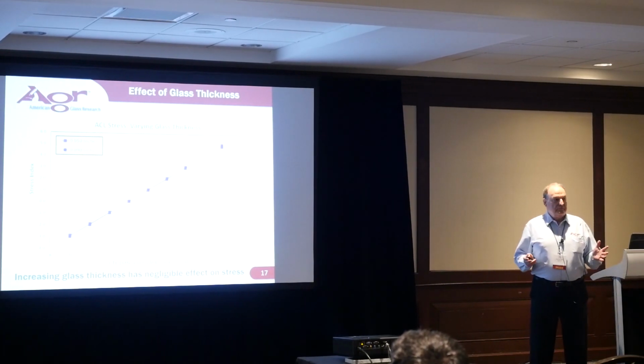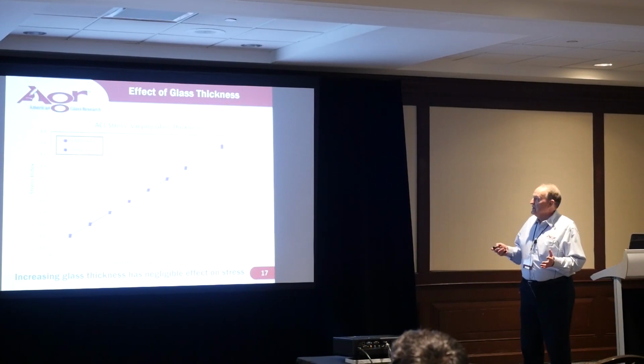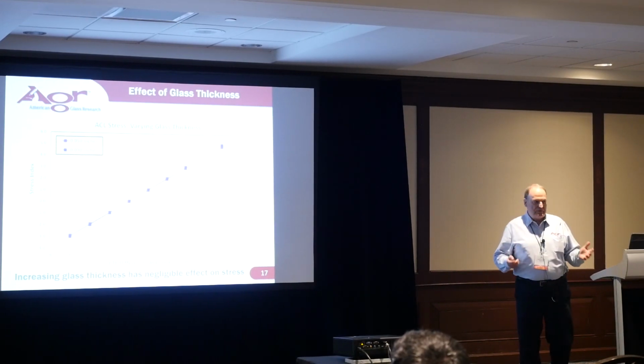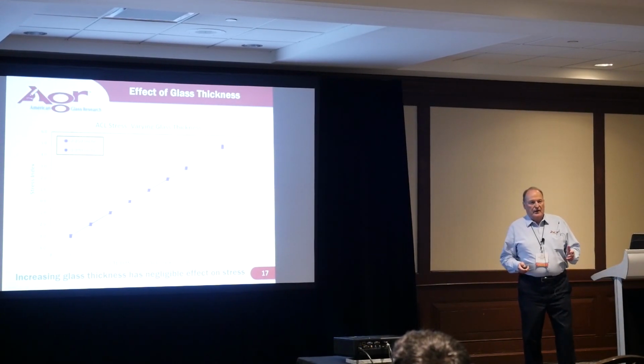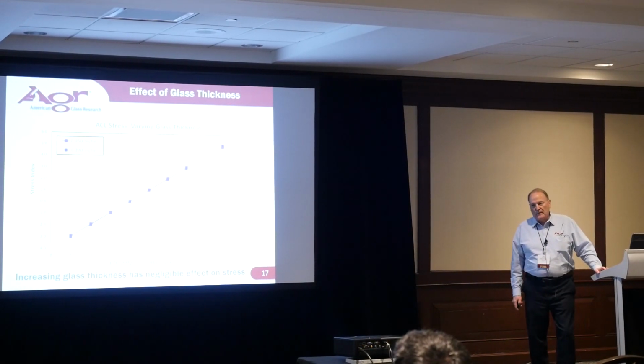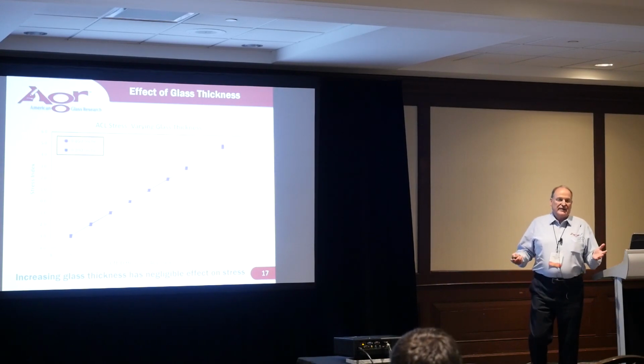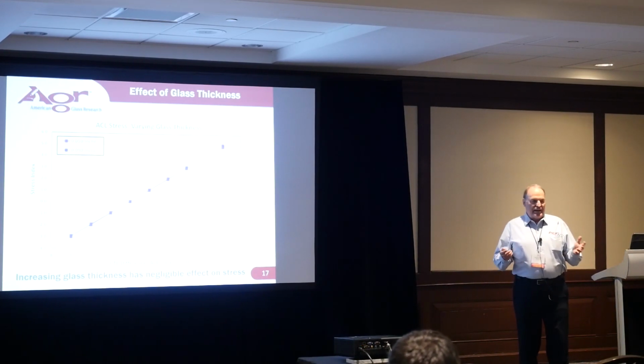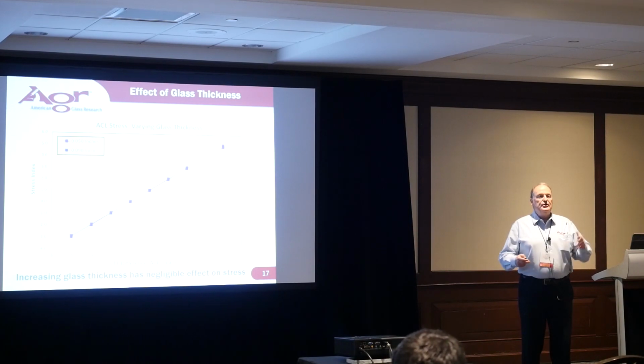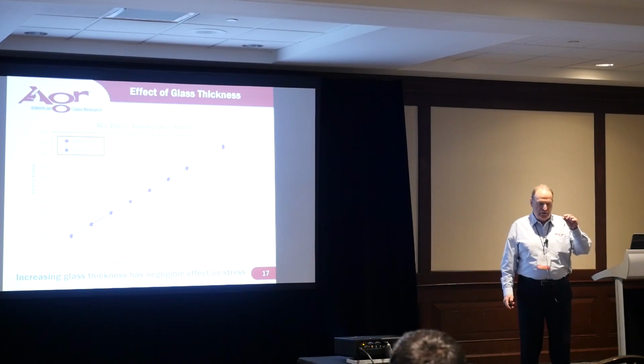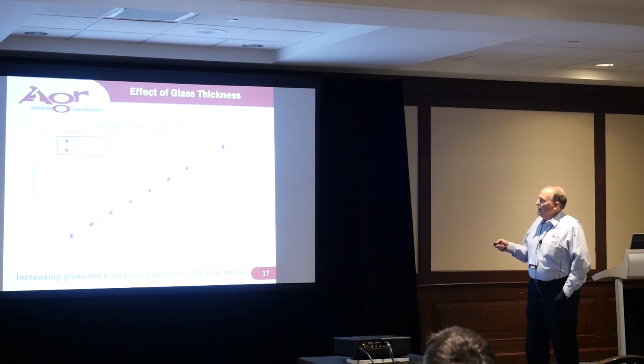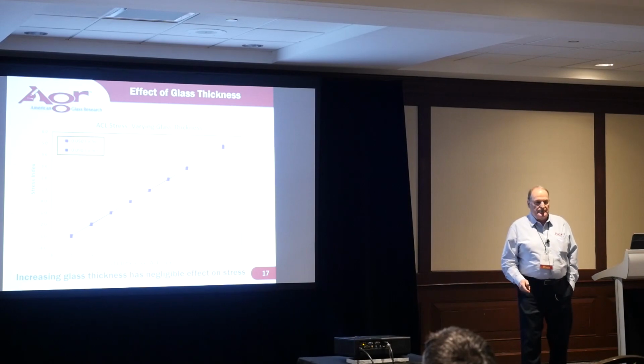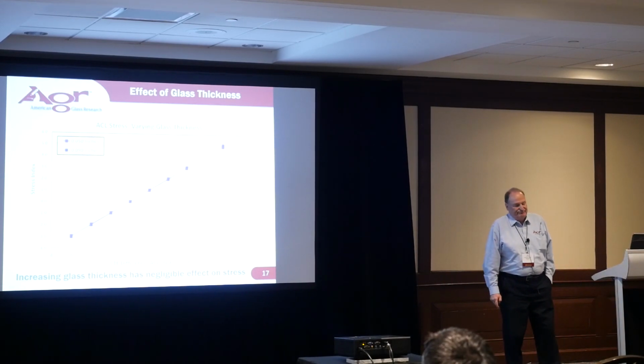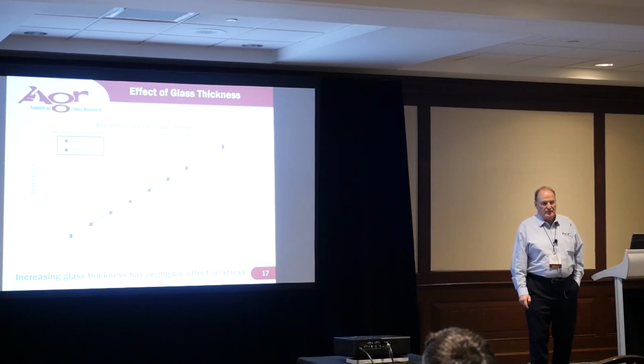We have the same plot, same kind of interpretation, except now we're looking at the effect of the glass substrate thickness. Now realize that our ACL is on the order of 1/1000th of an inch, and the glass is between 50 and 90 thousandths. It's huge compared to our very, very thin ACL layer. And what we saw was, again, some slight difference depending on the substrate thickness, but overall totally meaningless, totally negligible.